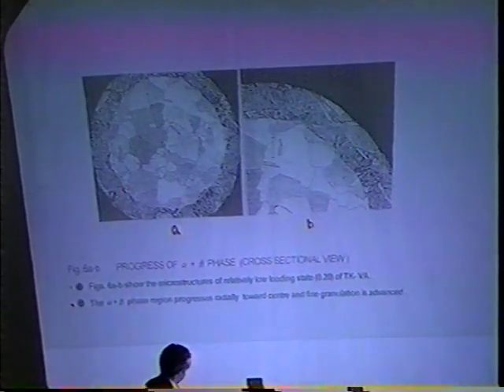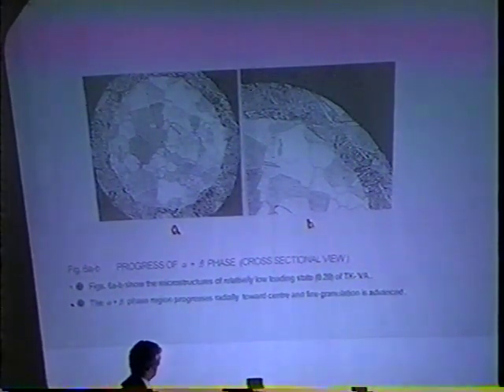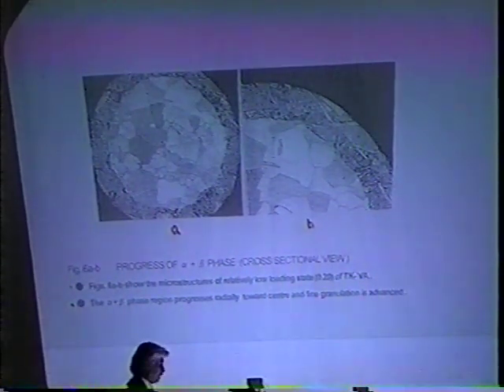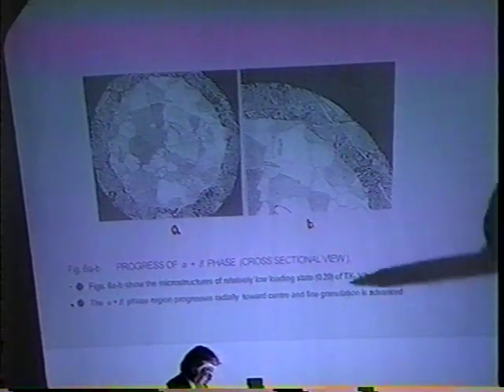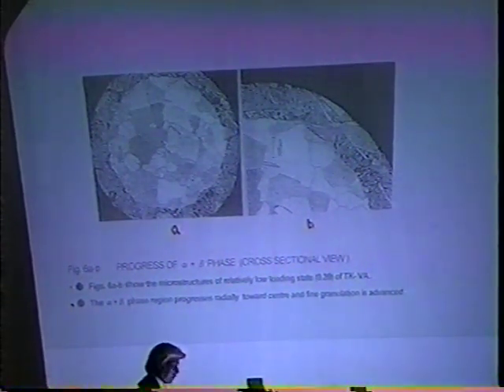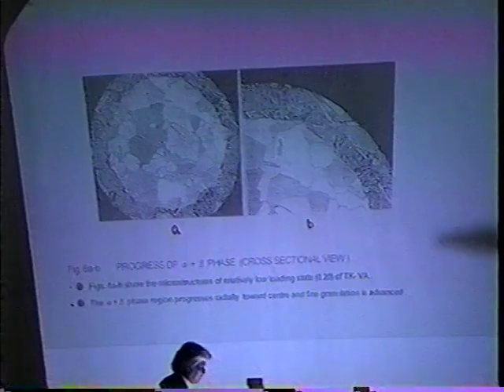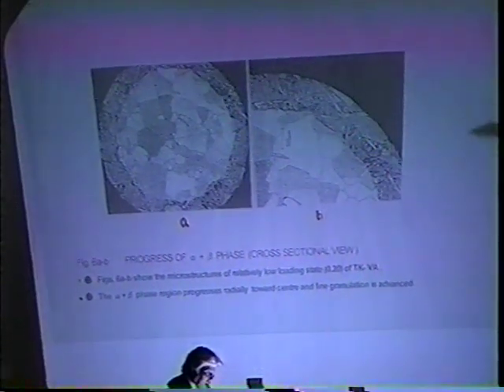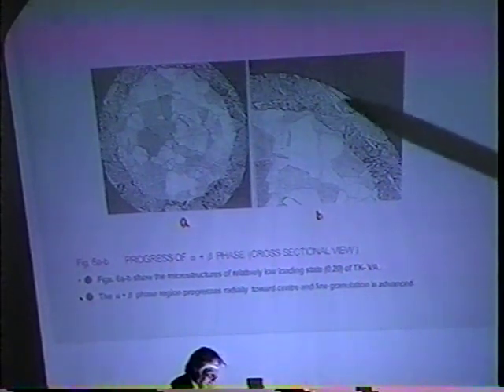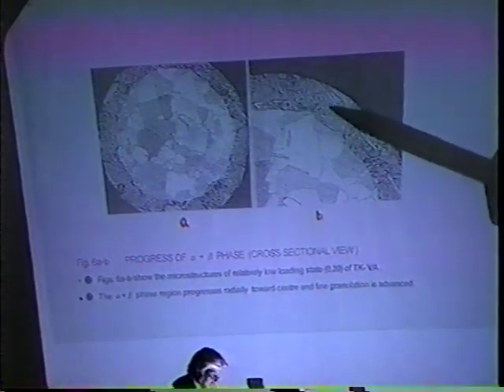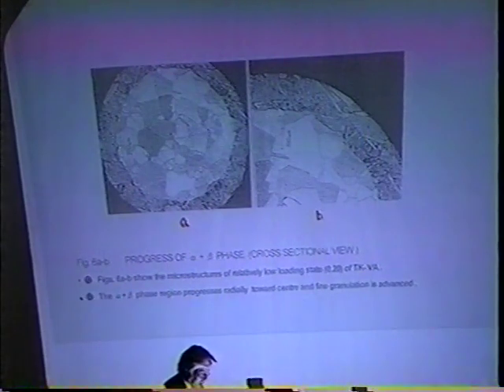This structure is shown in a relatively low loading state. In this case, 0.2. And this here, the cross section of here. And the alpha plus beta phase progresses laterally towards the center, or the alpha phase shrinks towards the center. And also observe the microgranulation is advanced in this alpha plus beta phase.